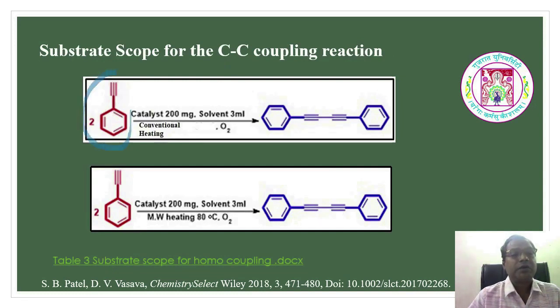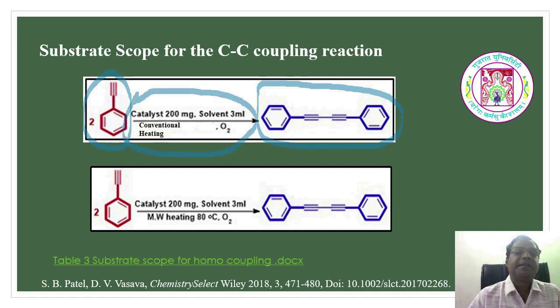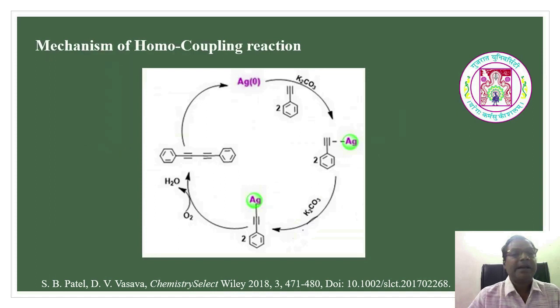In the same way, the terminal alkyne is utilized, and with C-C coupling, the homocoupling of the terminal alkyne takes place. And this is the conventional method where around 120 degrees Celsius temperature was used, but the same thing was reported by us where it required only 80 degrees Celsius temperature and 200 milligrams of catalyst, and a 98% yield is reported by using the Ag nanoparticles.